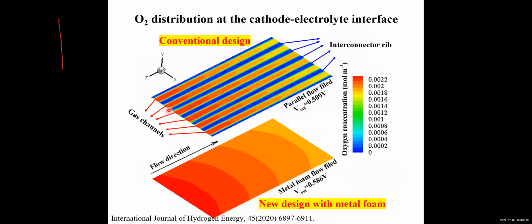So here are some simulation results. For the conventional design, we have the channel and the rib. Under the channel, the oxygen concentration at the cathode electrolyte interface is pretty good, we have high oxygen concentration. But under the rib, the oxygen concentration is pretty low because oxygen diffusion under the rib is difficult. So the local cell performance is poor, which decreases the average power density of the whole cell.